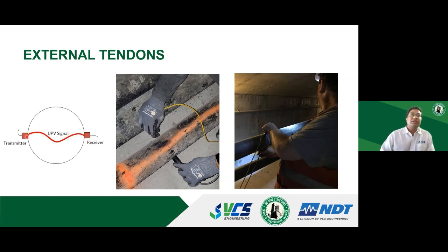You have an idea of the exact diameter of the duct, and that helps us know if the defects are present and to what extent the defects are present. Usually we do this testing at 10 o'clock, 2 o'clock, 4 and 8 o'clock positions. And that way we perform a comprehensive testing to see if the defects are present and to what extent.